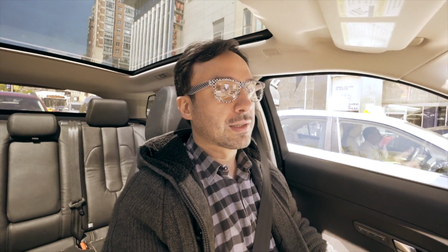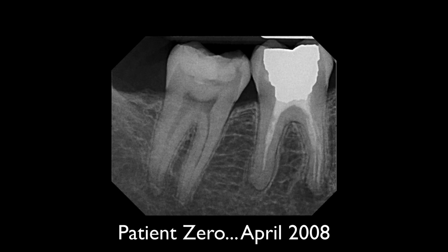Now, I say that emphasizing that, before you take any material clinically, you have to do a bunch of extracted teeth. And as we do here with the residents at Harvard Dental School where I teach, we have everybody do a bunch of extracted teeth before they see any patients. And anytime you get a new technique, you really have to be conscientious in trying to make sure that you apply the technique on extracted teeth first before you do it on actual teeth. And basically what I did here is I did a bunch of extracted teeth first, and then I took it clinically and I did this case.